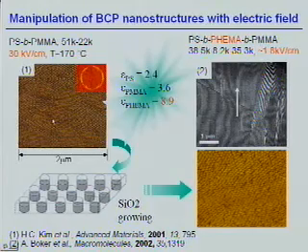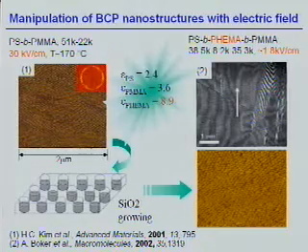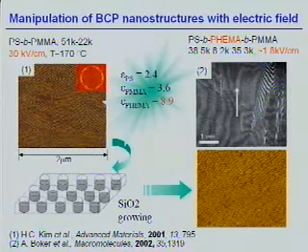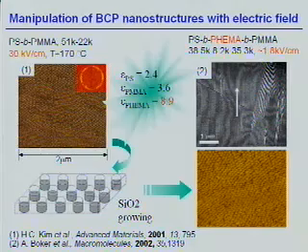And the second conclusion is that this nanostructure of block copolymer can be aligned with external electric field. Okay, I will be happy to answer any question. How do you dissolve it? You can dissolve it by solvent, right? The one of the block copolymers. Okay, for PMMA, you can use ultraviolet ray to make it decompose, and then use acetic acid to dissolve the MMA. Right, I see. Basically, cross-link polystyrene when you have this ultraviolet light, you can dissolve the other component.